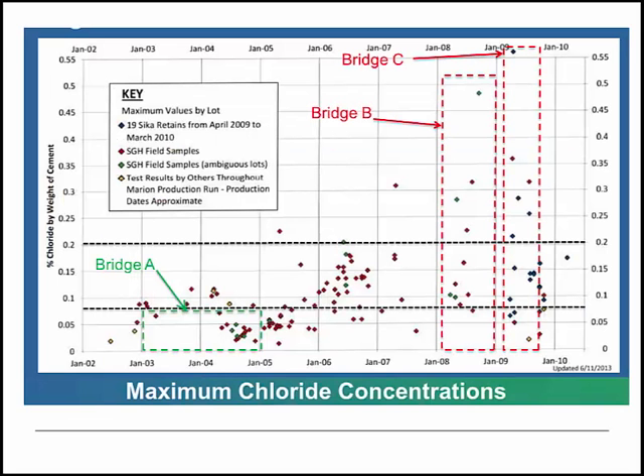So going back to the graph that Brian showed previously, again, the chloride contents that were captured at Bridge A were all less than the PTI specified limit, which is the lower black line, and those data points are captured in the green box on the left, generally low chloride content. As we move further along in the Marion, Ohio timeline, there gets to be more variability and certainly higher chloride contents, and many of those were captured through the sampling that was done at Bridge B and Bridge C.